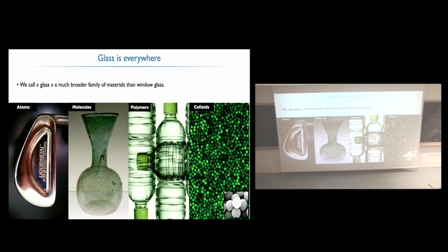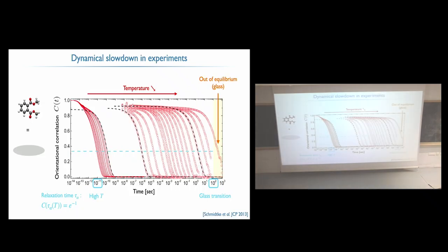And then at larger scales, if you have colloidal particles, so these are small particles of around a micrometer, if you really compress them, it's similar to cooling, then you get a very dense paste, which flows on very long times, and this is also what's called a colloidal glass. So this is very, very generic, and I wanted to describe a bit more what the dynamics does.